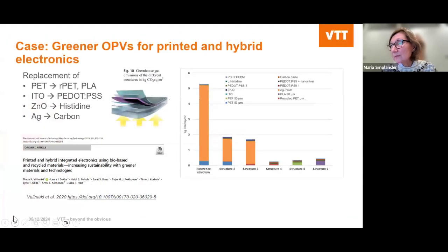So I still want to continue a little bit about this material selection. This is a work by my colleague Maria Välimäki, who has been studying a lot on the printed OPVs, the solar cells, and has been looking at the possibilities to replace the materials with, let's say, more environmentally friendly options. And in this LCA study, what could be seen is that the reference structure is changed to a structure where the silver, instead of being a compact surface, has been applied as a silver grid. So already this change is considerably decreasing the CO2 equivalent of the printed OPV.